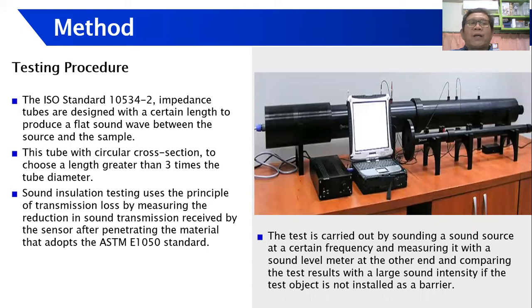Testing procedure. The ISO standard 10534 impedance tubes are designed with a certain length to produce a flat sound wave between the source and the sample. This tube has a circular cross-section, with a length chosen greater than 3 times the tube diameter.